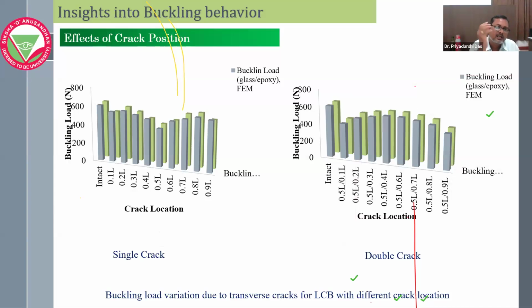Here, since it is buckling, we find the maximum reduction happens at 0.5 L, and for the second crack, 0.5 L is the constant. For vibration analysis, for the cantilever beam, 0.1 L is the critical position. Here for buckling, 0.5 L is the critical position. And for the two cracks, you can find 0.5 L and 0.1 L are critical. So similarly, if it is 3 cracks or 4 cracks, there is a pattern. Through that pattern, we can analyze the number of cracks in an element.